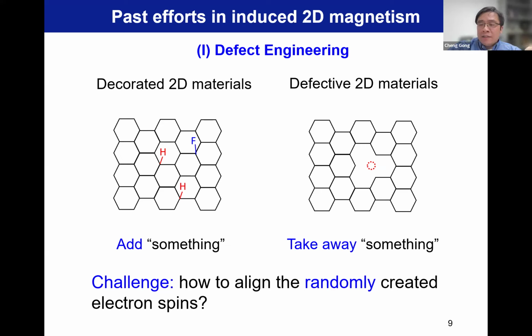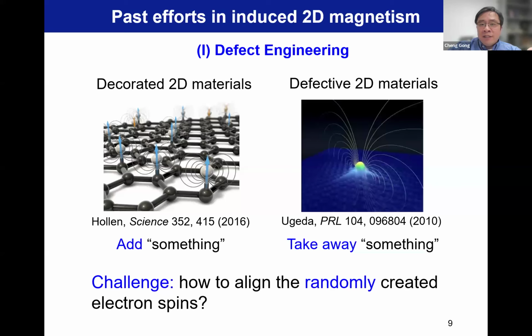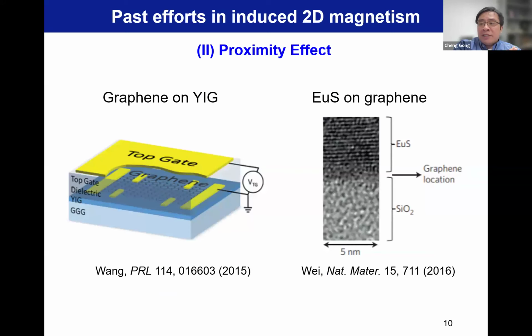So far, I don't think there is a consensus in the successful development of long-range order by this method. The other method is very smart, basically universally effective. If you allow me to say like this, you put a non-magnetic 2D material like graphene with a magnetic material with a clean interface. Then you will see the interfacial wave function overlap between the two materials will spin polarize graphene or other non-magnetic 2D material.